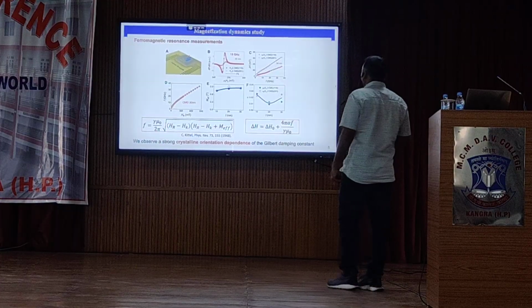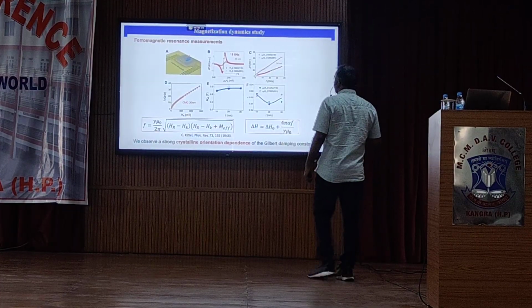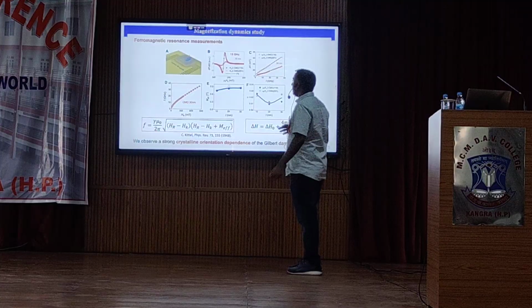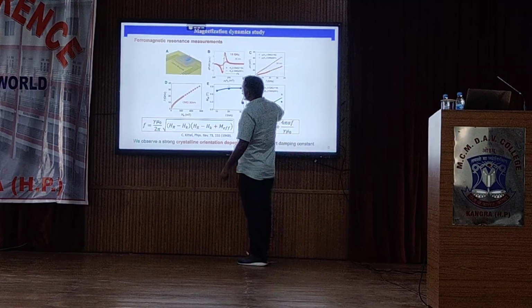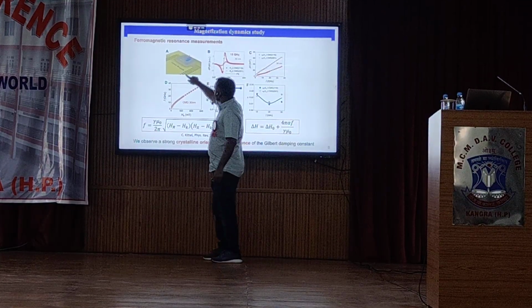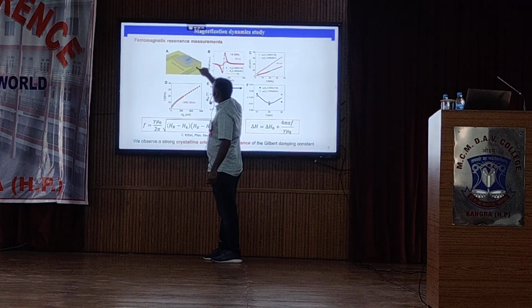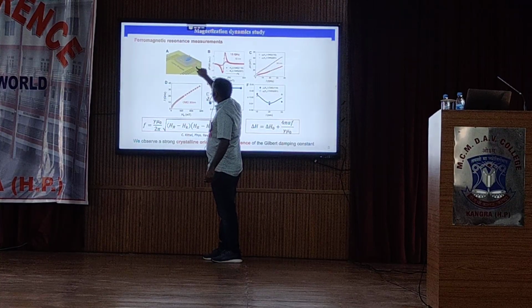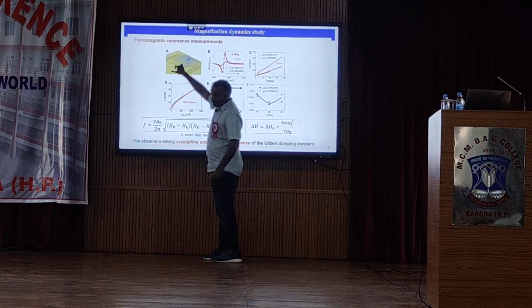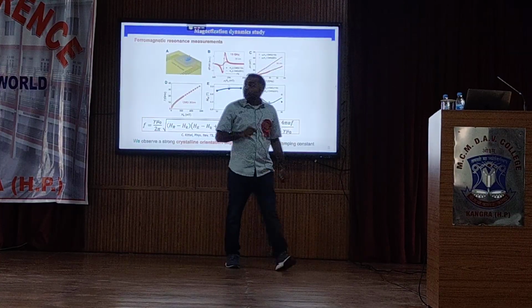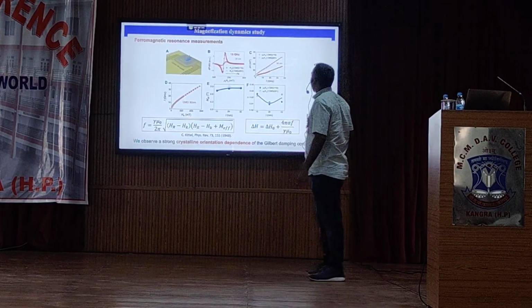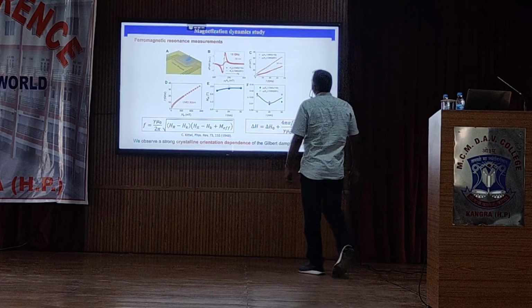What we do for the magnetization dynamics before making the nanoscale devices: we have the ferromagnetic resonance measurement setup here, where you can see the coplanar waveguide. We have a microwave signal on this conducting line. We place our thin films over this conducting line, and then we study the magnetization dynamics of our thin films.